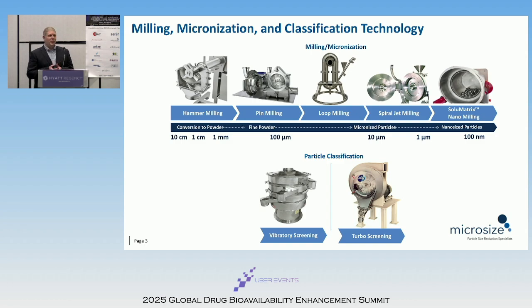We also use turbo screens to help control the form of your compound. So micronization tends to dry materials out. If you have a hydrate, that's something that you want to avoid. So we could use a turbo screen to separate the individual particles on metric ton scales, humidify the room, and then basically rehydrate your material after a micronization.